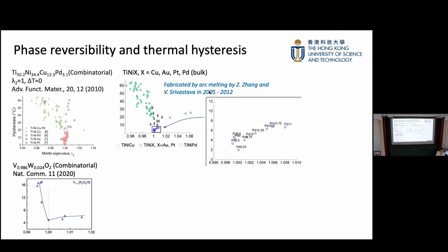Those data are produced by a simple combinatorial method. People have a target and mix different elements at different compositions and make a very big disk. At each place, the composition changes, so the lattice parameter changes, and locally the compatibility condition changes. And people directly calculate the thermal hysteresis for each composition on that big area. People call it a combinatorial experiment. That's the thin film data, and people show that the thermal hysteresis is really minimized at lambda 2 equal to 1. I believe Dick James already showed that many times to this community.